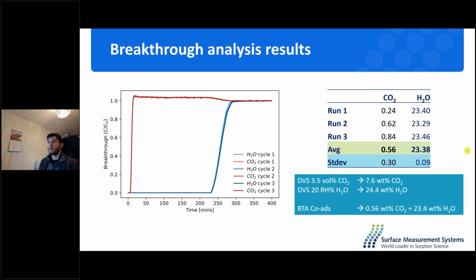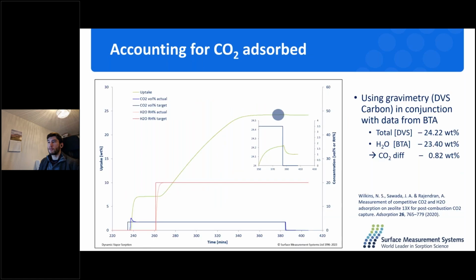So even though it gives you a good picture of co-adsorption, the error bar over here is much higher than you'd want. So one way to go about obtaining an accurate CO2 uptake in the presence of water is to combine the two results, the two instruments.